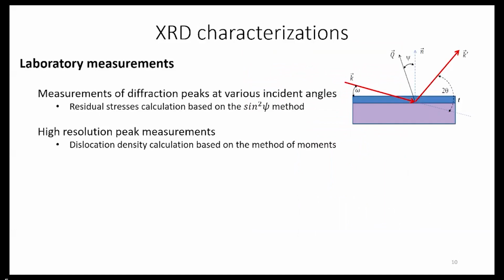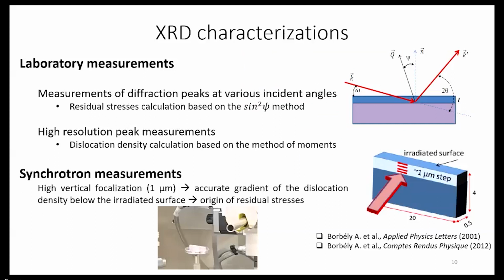After these irradiations, we are doing some XRD characterizations, including laboratory measurements in order to compute the residual stresses below the surface, and also some high-resolution peak measurements in order to calculate the dislocation density, and to be more precise in the computation of the dislocation density gradient below the surface.